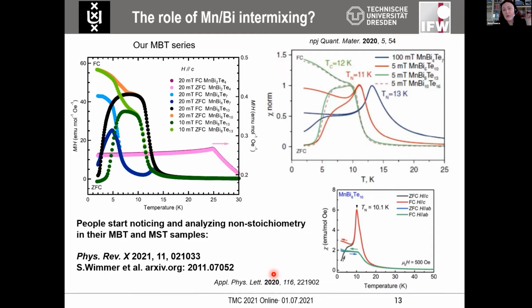This is notoriously difficult because, first of all, you have very small values of these additional concentrations, and second, it's difficult to obtain these crystals. Meanwhile, there are new studies emerging. So it was also recently discovered that an antimony analog of MBT can exist. And I will be moving to that phase in a second, showing you that there the disorder phenomenon gets even stronger and it becomes possible to somehow study it not under a looking glass, but let's say at face value, which is already being done.